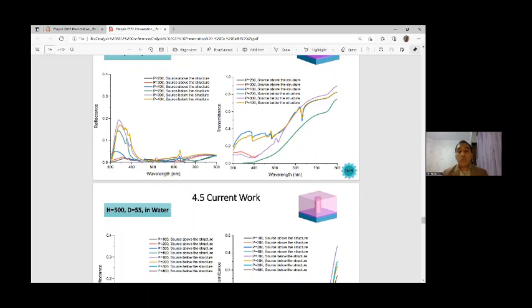In structure 2, as you can see, the reflectance from the TiO2 side, I mean the above, is less than from the ITO side, I mean below the structure. However, they have the same transmittance. Therefore, the absorption on the TiO2 side is higher than that of ITO.